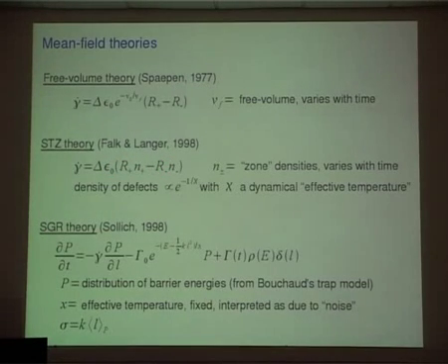And the idea is simply to say, okay, we know that there are these many local transformations, so we need to write an equation where the strain rate is just the sum of all these events, and we try to guess or write a theory for what is the rate of these events. And the problem is that in all these theories, these local shear transformations are assumed to be independent. They're just thinking that, okay, they are local shear transformations. We try to write rate equations for these shear transformations.